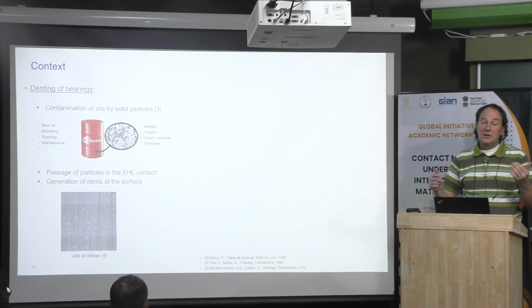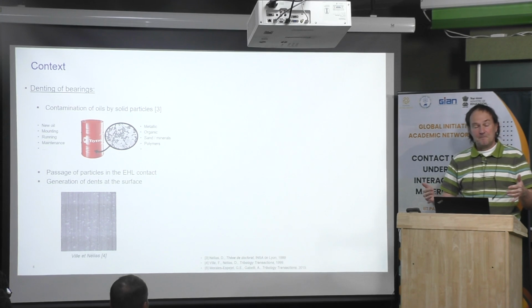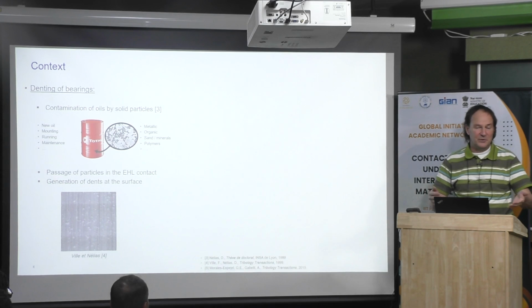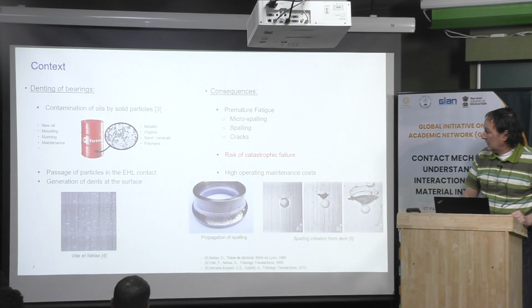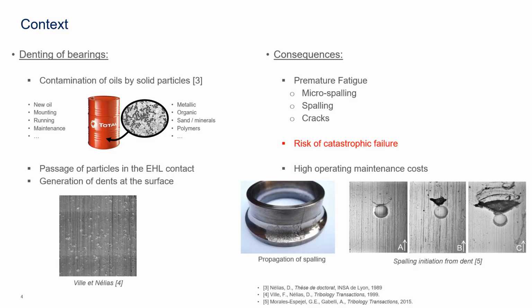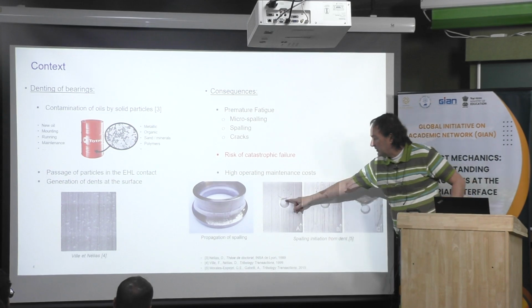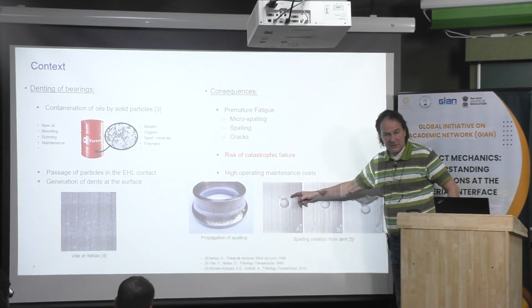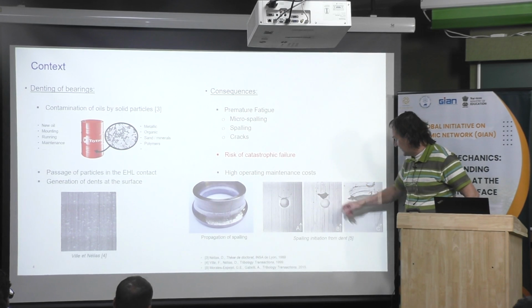And when you do some maintenance, you also have to be careful not to ingest particles. For example, when you are outside, if there is some wind, if you have some sand outside, you have to be careful not to open the oil reservoir to renew the oil, because you will ingest a lot of particles. And typically, this is what will happen after a dent. Then you can see here the early beginning. First, you can see a crack, and then the crack will start to propagate, and like that.